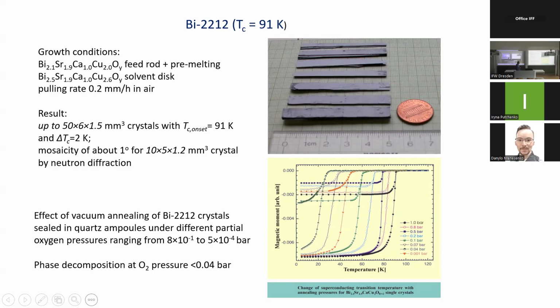Again, the mosaicity of the crystal is still, I would say, low. It's about 1 degree for a relatively large sample. And for the optimally doped crystals, TC is around 91K, and we could prepare either underdoped samples by annealing in vacuum, and even overdoped, but it's still harder.